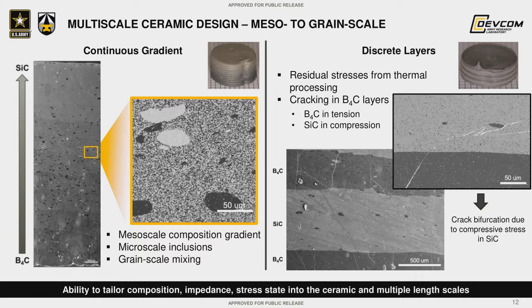So when we've analyzed these parts using scanning electron microscopy and other techniques, we can see that we've been fairly successful in creating the controlled microstructures that we desire. So in our continuously graded parts on the left, you can see at the top on the silicon carbide portion, you have mainly silicon carbide, and then at the bottom you have mainly boron carbide. But we do have some issues with obtaining full mixedness between the materials, partially from agglomerates within the individual inks as well as during the mixing process.